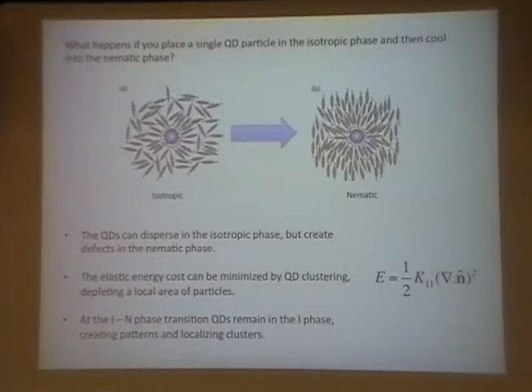Now, we can relieve the elastic energy cost of that by particles clustering together. So if you think about your liquid crystal and you have particles everywhere, cool into the nematic phase, if the particles are able to group together, you'll be able to minimize the number of local defects. And that's exactly what we see. When you try to disperse the particles in the liquid crystal, if the concentration of them is enough, they'll deplete from a local area and cluster together. And it makes sense, if they're able to find each other, they form just one defect, it's a big clump of particles. You can think of it as a kind of coming out of solution, but not a total phase separation. You know, they go to a defect. This is really what you think could be happening when you have particles going to a defect. They just cluster in a local region, meaning they remove themselves from the liquid crystal, so we minimize the energy cost by clustering.